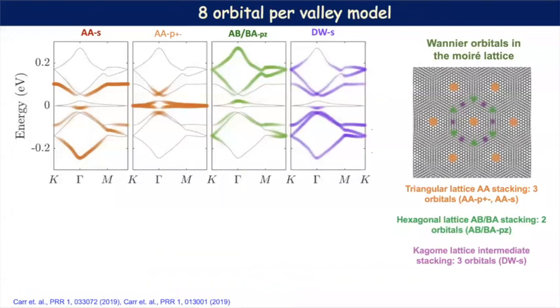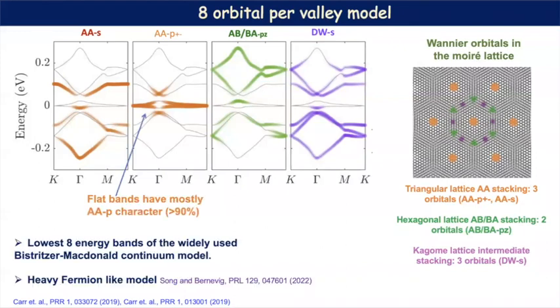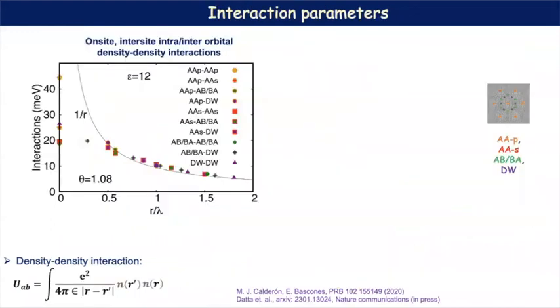But out of all these, I just want you to focus on these ones, which you can see have maximum overlap with the flat bands. Because they characterize the flat bands, they are going to be the key players in the correlation physics. But I also want to emphasize that these orbitals cannot cover the full flat bands, and there are these leakages, as you can see here near the gamma point. That's related to the fragile topology that I mentioned in the previous slide. So at gamma we have contributions from other orbitals which are less correlated, where we have the itinerant electrons. In this way, these localized orbitals are also coupled to itinerant electrons in these other orbitals.